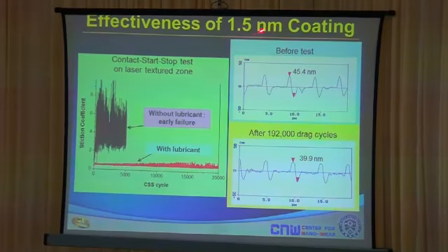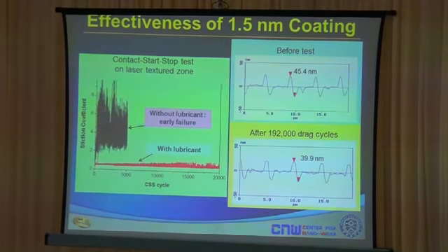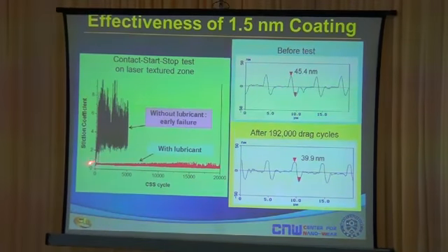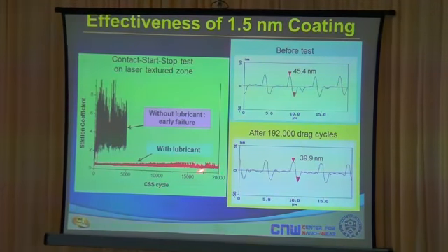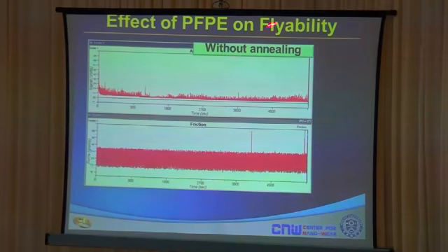With a 1.5 nanometer coating of the PFPE lubricant, this is the stiction coefficient that you get over 20,000 CSS cycles. Without the lubricant, you will see that the friction is very high and the hard disk will fail immediately. That is the power of this 1.5 nanometer lubricant, which is not really a liquid. It's semi-solid, but it works tremendously well in hard disk drives, and this is what makes today's hard disk drive work.